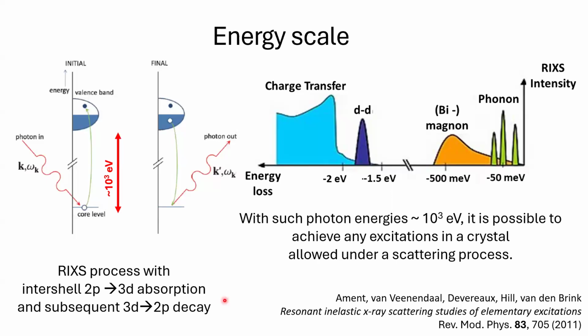What about the details of all these enumerated advantages? Energy scale means that if we use photons with X-ray energy, we have a RIXS process with inner-shell absorption from the 2p shell to the 3d shell, and subsequent decay from 3d to 2p. Because of this huge energy, around 1000 eV, it is possible to achieve any excitation in a crystal allowed under the scattering process: phonon, magnon, dd excitation, charge transfer excitation. So this energy scale gives us a unique possibility for studies.